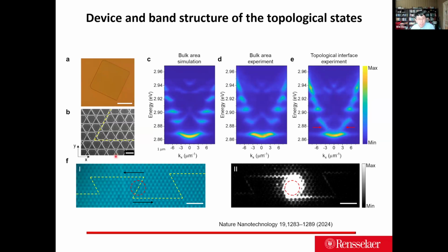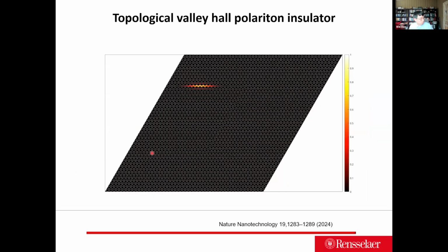This is much better. And we also emphasize this: the smallest feature of the structure we make here is about 100 nanometers. This has never been possible with gallium arsenide, because gallium arsenide typically, based on my colleagues' education of me, is always a few microns, 2 or 3 microns. You cannot make the structure smaller because with the etching of the DBR, the quantum well will also be damaged on the edge. Those are relatively challenging.